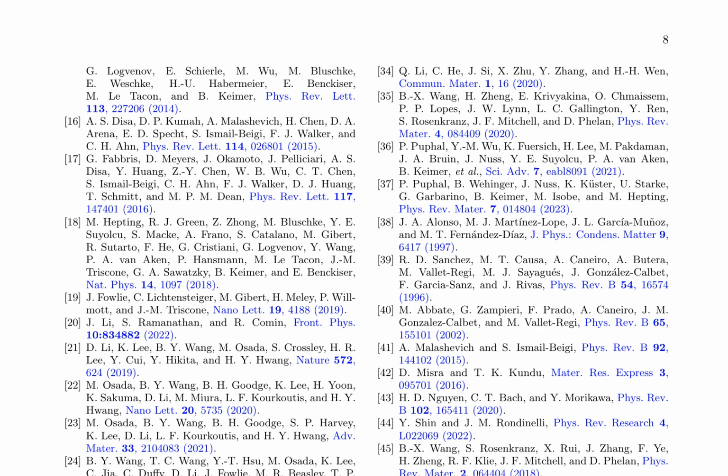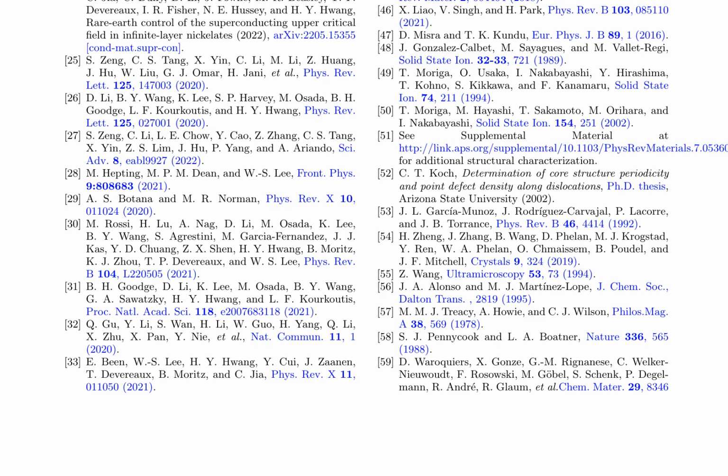High-resolution synchrotron XRD and future STEM studies on crystals after prolonged topotactic reduction can provide more insights into the structural refinement and the potential transformation into a square planar, octahedral structure with a square root 5 ap times square root 2 ap supercell. The observed oxygen vacancy ordering with apex-linked pyramidal units is distinct from all previously identified RNiO3-δ lattice structures. The study suggests that the exploration of potentially emerging magnetic order in PrxCa1-xNiO2.75 will be